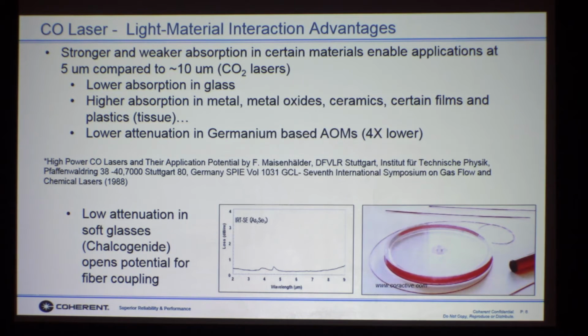And so the advantages of 5 microns are the different absorption of material. And I'll show you some examples how the lower absorption at 5 microns compared to 10 microns in glass is really important. All of us know that typically higher absorption is important in materials processing. And again, compared to 10 microns, CO2, there's higher absorption in metal, steels, metal oxides, ceramics, certain films and plastics, and even human tissue. So there's a lot of potential there. Then there's lower attenuation in AOMs, which are often used in front of CO2 lasers. In fact, the attenuation is 4x less. And there's an interesting article dating back to '88 that has a bunch of different very interesting applications that were done on, again, one of these big lasers that lasted 10 or 12 hours.